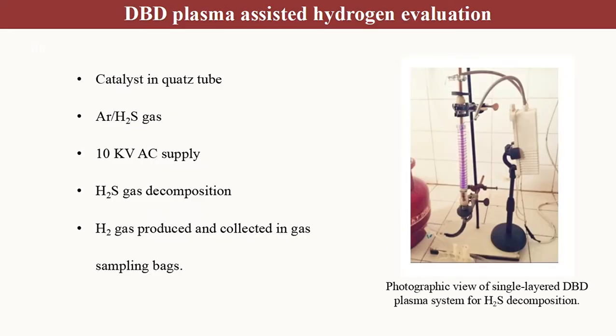DBD plasma assisted hydrogen evolution. The DBD plasma was sustained with a fixed AC source of 10 kV, where plasma-produced species and UV radiations were used to activate the catalyst to break the hydrogen sulfide molecules under ambient conditions.